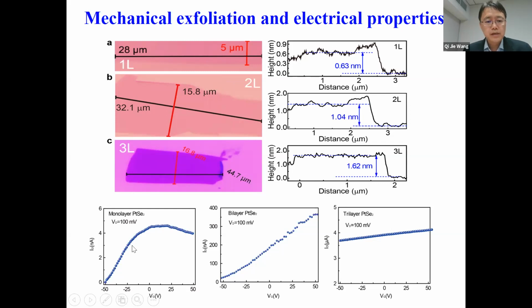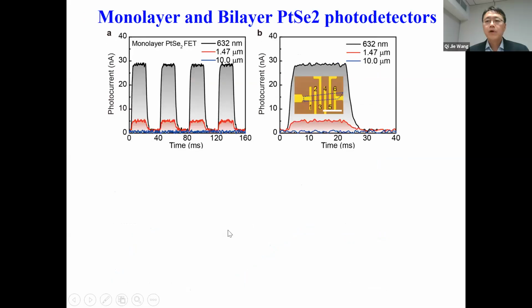Through electronic measurement, IV curve characterization, where the y-axis is current and the x-axis is voltage, we found that the three-layer and thicker samples have ohmic contact, while the monolayer has a relatively large bandgap, so you see this large band. The two-layer sample has a relatively linear curve, but still some bending right here, which shows that the bandgap of the material is narrow. Then we fabricated FET photodetectors based on both monolayer PtSe2 and bilayer PtSe2.